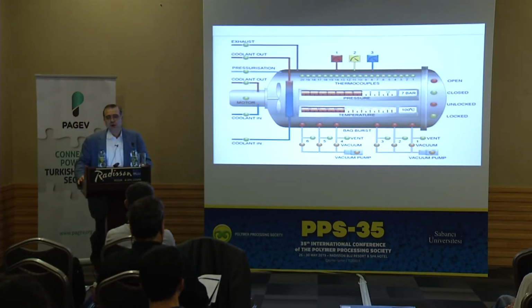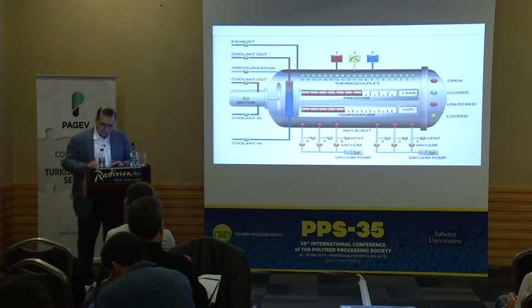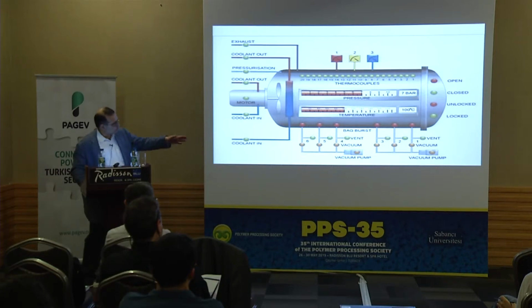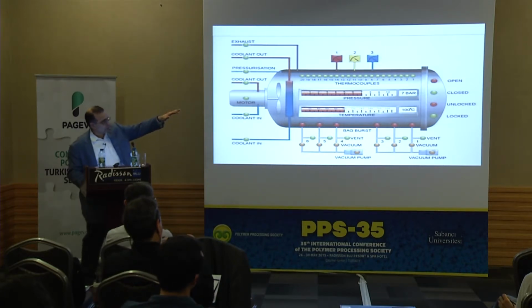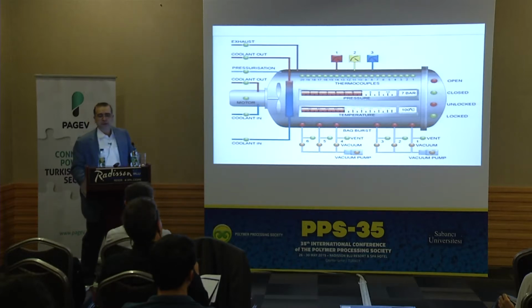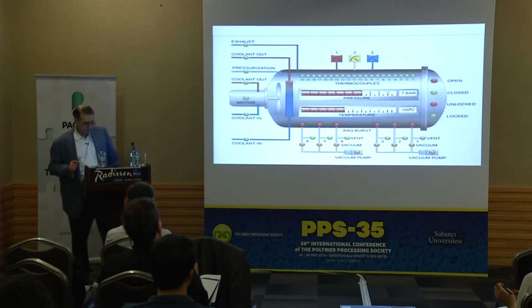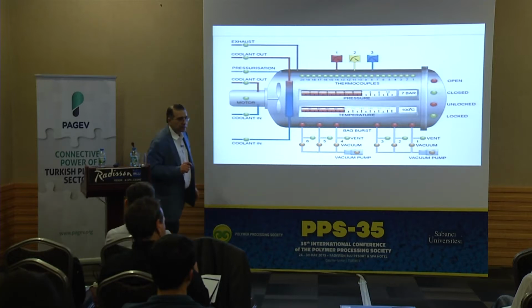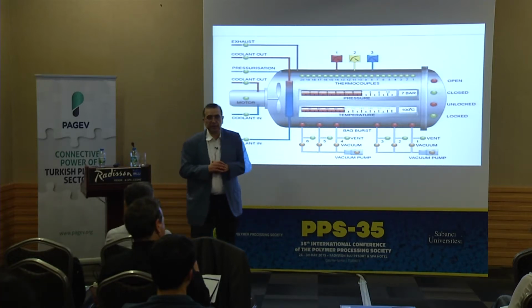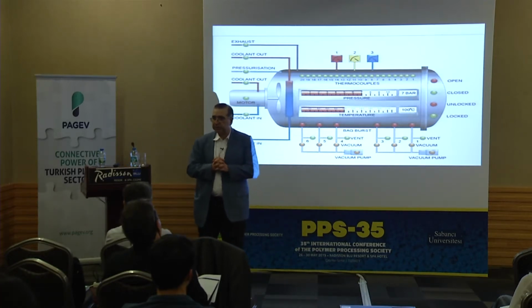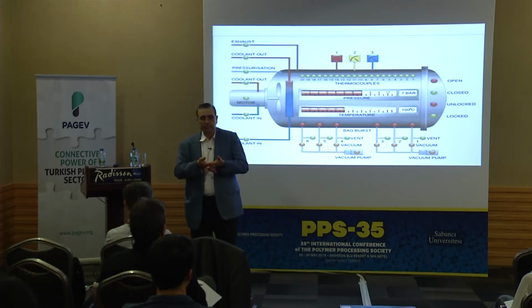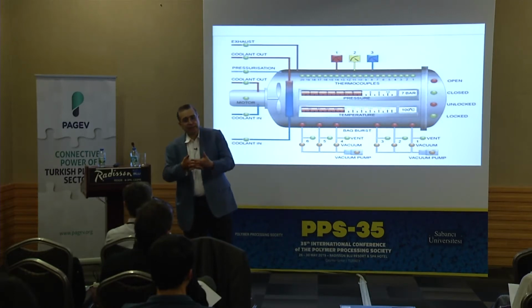Vacuum is usually kept throughout the cure cycle in the bag, so it's always under vacuum, and then you ramp up the temperature and the pressure, you hold it 3-4 hours, and then you cool it down. Now, this is called the cure cycle: time, temperature, variation of temperature and pressure inside the autoclave. People spend a lot of time to optimize the cure cycle.